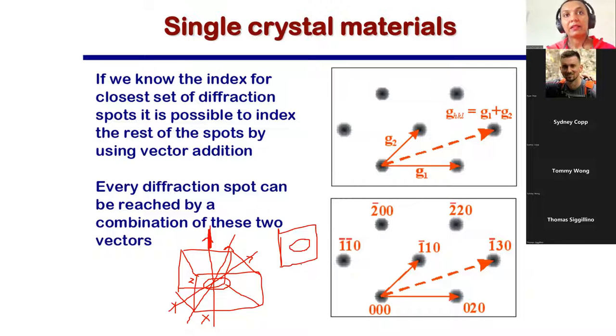Whereas another person tries not to look at an open plane, but only looks from the top. So for him, the dislocation loop will only look like a small line like this, because he is looking from here. So the bottom part of it is hidden under it. Basically it is like this, but he is not seeing this part. It's simply a question of perspective. So what happens is, you try to have information along 1G, which gives you an open loop. In other conditions, you will find an edge loop.